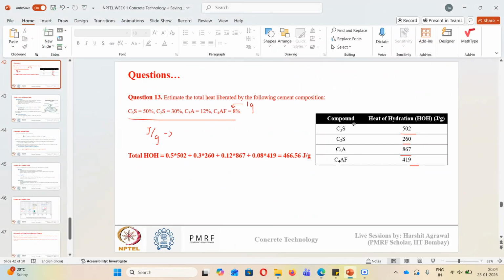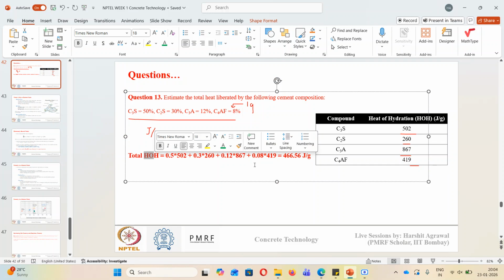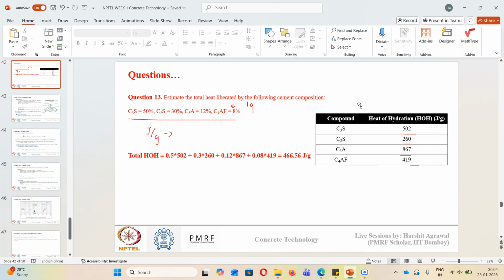When we vary the proportion of cement, in the next session or the one after, you will talk about different types of cement. When we talk about different types of cement, you will see that these proportions vary. When the proportion varies, the total heat of hydration liberated by different cement systems will also vary. In hot weather concreting, we want a cement which has lower heat of hydration. In cold weather concreting, we want a cement which has higher heat of hydration. So we can judge from the composition.